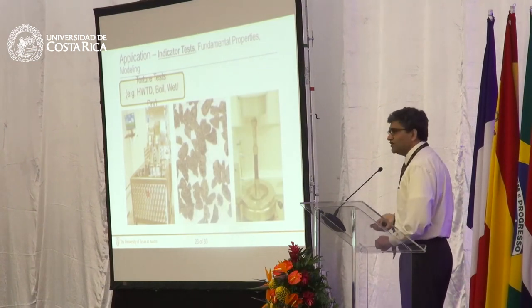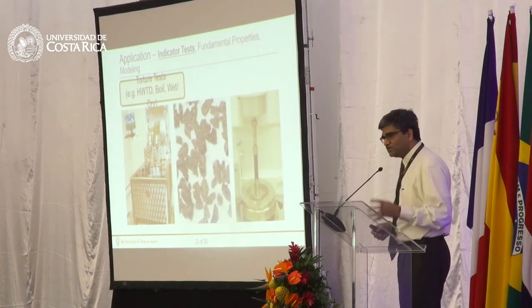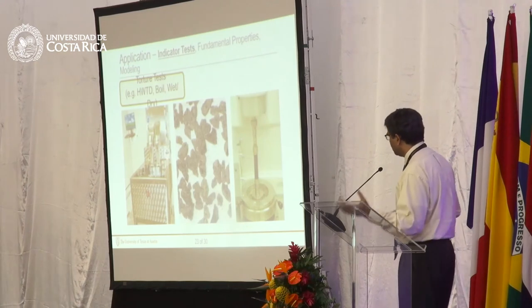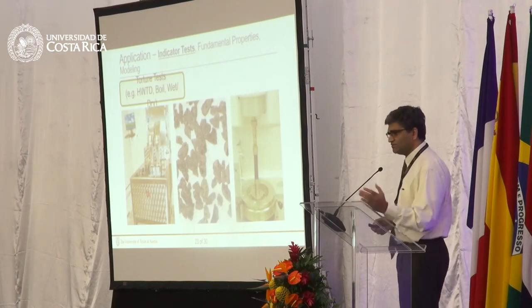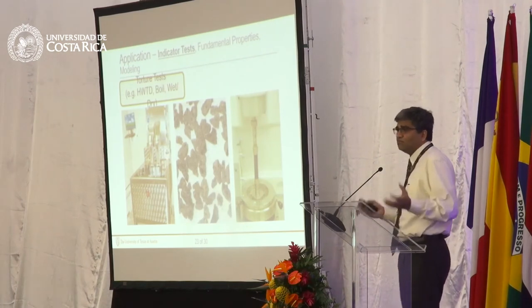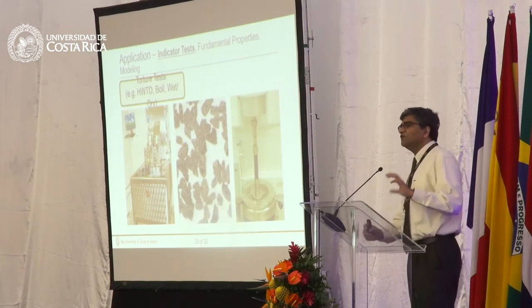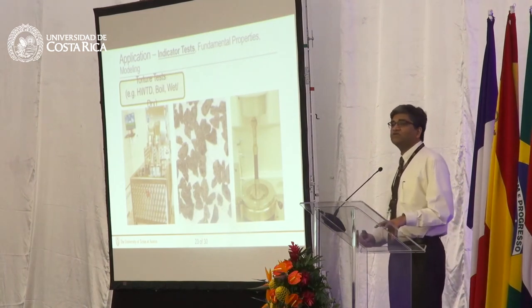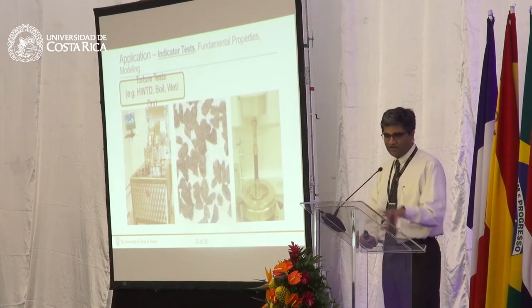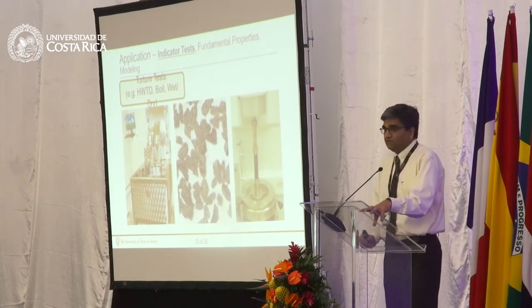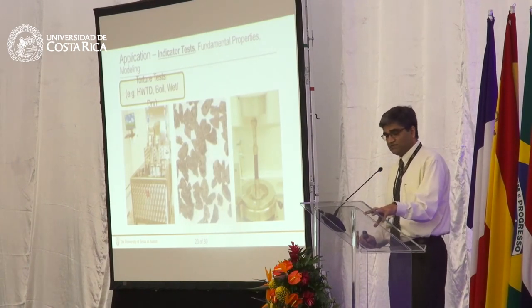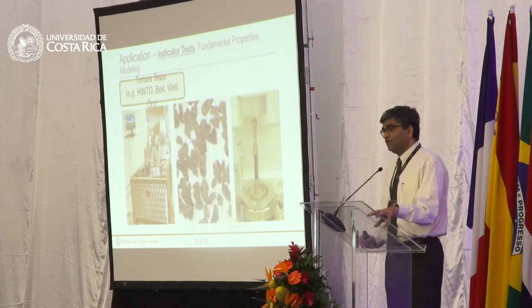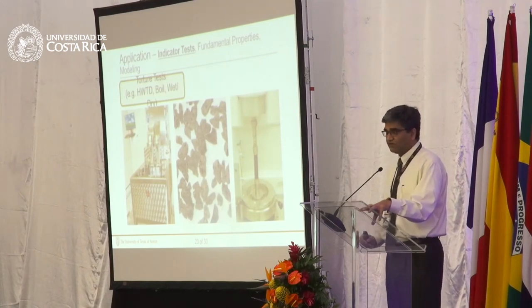The wet to dry ratio, you can run the indirect tensile strength ratio, you can run fatigue tests, you can run dynamic modulus tests before and after moisture conditioning. These are good tests, they're indicator tests. The only problem with these tests is that they don't tell you why. If I have a bad mix, that's all that's going to tell me, that this mix is bad. It doesn't tell me what is wrong with it, and how can I fix it.